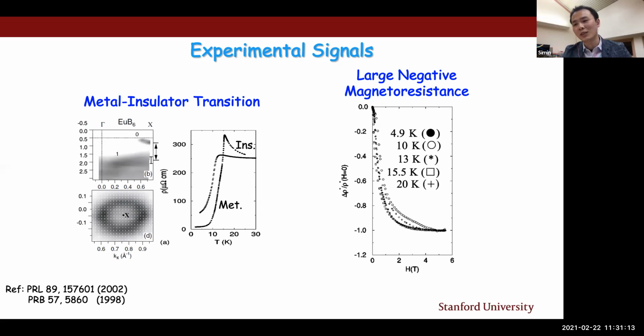Yes, first, the Weyl semimetal has potential applications in devices. Another thing is that in materials, the Fermi level usually cannot be exactly at the Weyl point, which means you will have some trivial hole or electron pockets that give you trivial signals, and it's not clean.